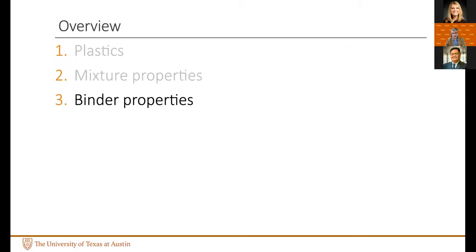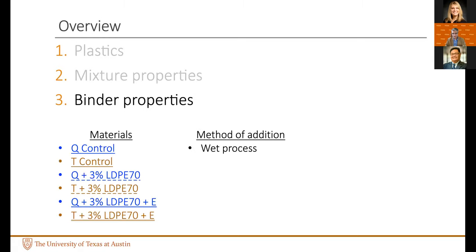And going into a smaller lens scale, looking at binder properties, we also did this, except that in this case, we had the Q and T, the two different binders, and the two different binders with LDPE. But we added two more binders here. This was the plus E shows plus alloy. We worked a little bit with Dow Chemical on this, and their terpolymer that they use also is intended to be a compatibilizing agent that stops the separation of plastic and helps distribute the plastic in the asphalt binder a little bit better.